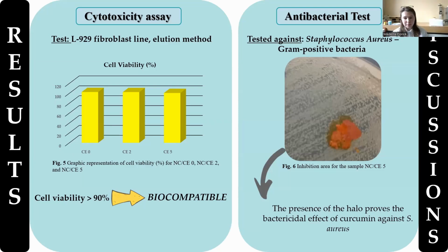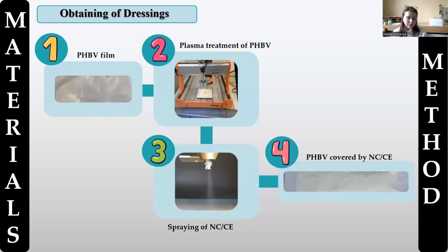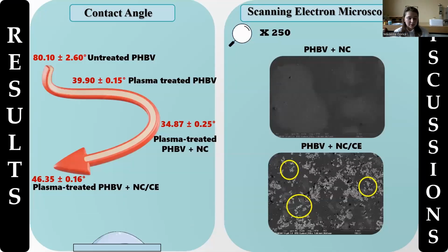around the sample. Going further to the obtaining of the dressings using a biopolymeric substrate, the PHBV film was treated with plasma, followed by the spraying of the nanocellulosic mixtures on its surface. One of the first analyses carried out was the contact angle, and we can see that the low value of the plasma-treated PHBV as compared to the untreated PHBV corresponds to the hydrophilic nature intended for the film.